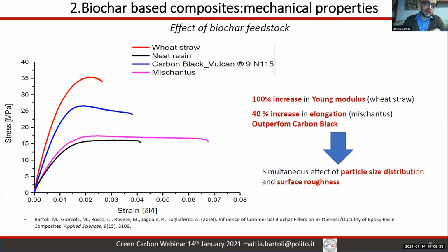The second one is more related to the roughness of the biochar particle surface. So smooth surfaces induce greater elongations, as in the case of miscanthus. Rougher surfaces, like in the case of wheat straw, induce brittleness with an enhancement of ultimate tensile strength and Young modulus. More important, here you can see that biochar-based composites can outperform carbon black ones. So biochar could be used as a sound replacement for high-tech fillers, but also for carbon black.